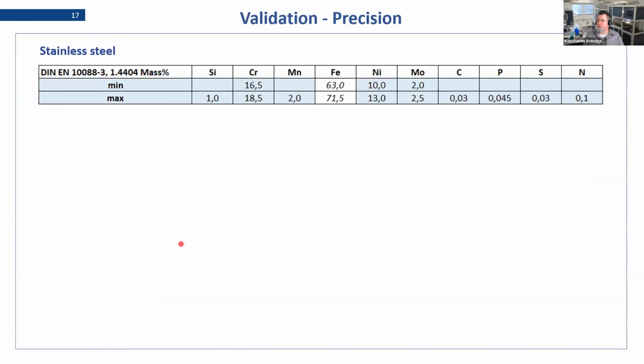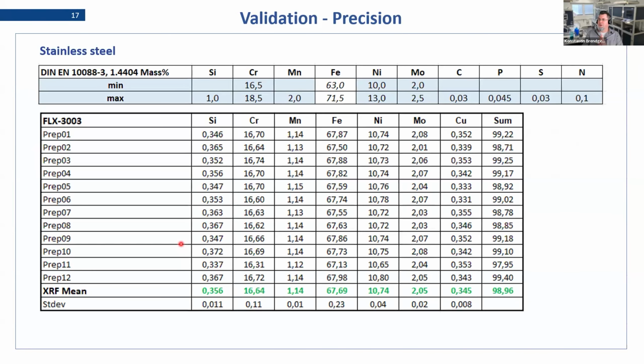And we get some more measurement data here in the end about the sample that we were talking about before. This is now measured with the application that we made from synthetic samples. In this case, we have 12 repeats. And as you can see, it fits quite well within the specification, but also the repeatability is very good, as we would expect from XRF.